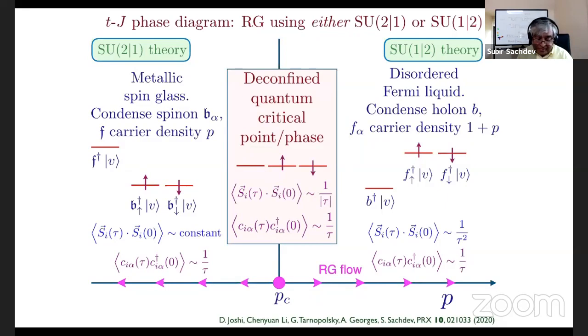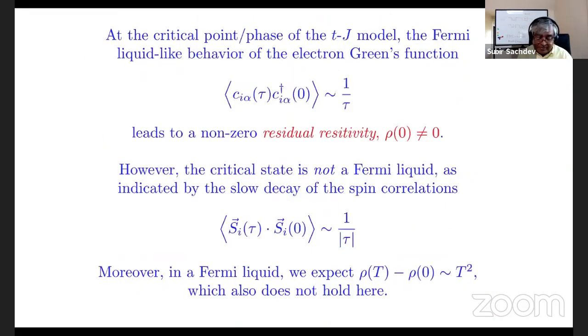So this is a calculation we recently did in this large dimension limit so that we have a sense of space. And what you find in that limit is that this Fermi liquid-like disordered Fermi liquid behavior of the electron correlations means that there's a residual resistivity which is non-zero. That doesn't mean it's a Fermi liquid because the spin correlations decay as 1 over tau. And as we showed, the resistance doesn't increase as T squared. So what contributes to resistivity? Well, to compute the resistivity, what you need, just like we considered for the spin susceptibility, is the subleading correction to this 1 over tau.